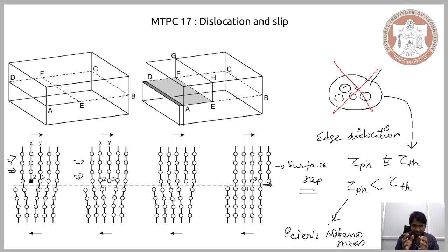So the plastic deformation is treated in terms of the movement of the dislocation, and when you consider plastic deformation as the movement of the dislocation, then the stress that is required to introduce the plastic deformation is referred to as the Peierls-Nabarro stress. Now, this is the reason why the dislocation was introduced in the first place. If you could recollect, the reason for considering the dislocation is the disparity between the physically observed stress to bring about the plastic deformation when compared to the theoretically required stress.